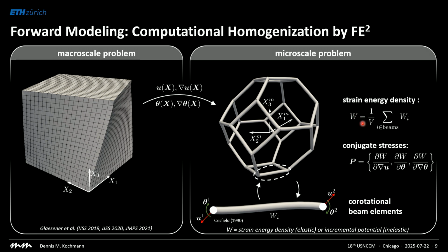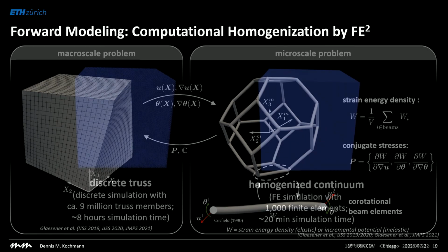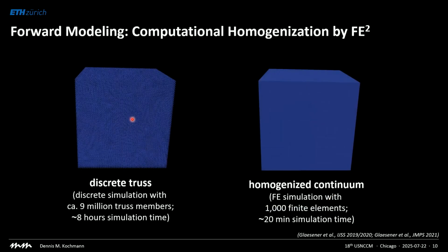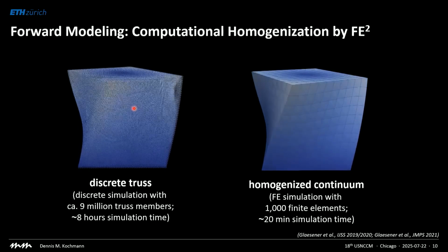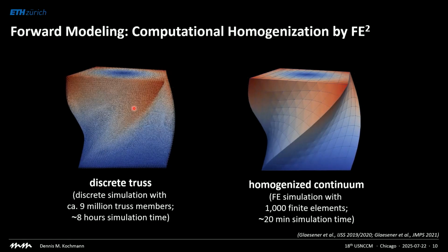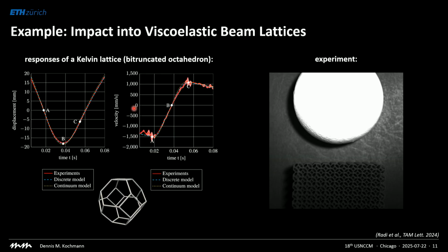If it's inelastic, you use an incremental potential. We can differentiate this energy with respect to whatever we pass down. This we pass back as the stresses. We can even compute a consistent tangent. But this is feasible. It's relatively easy because the number of degrees of freedom on the small scale are so low compared to what we have if you mesh and actually solve an RVE. So this can be used instead of simulating a truss that has millions of beam elements and takes hours to compute on a server. You can run this in a few minutes on a laptop based on FE square. And this works, of course, not just for show and tell, but this also works for actual problems.